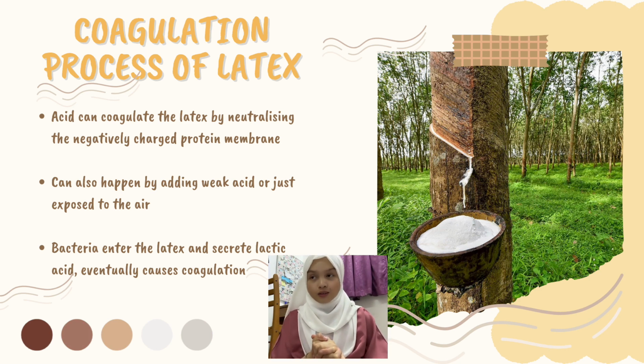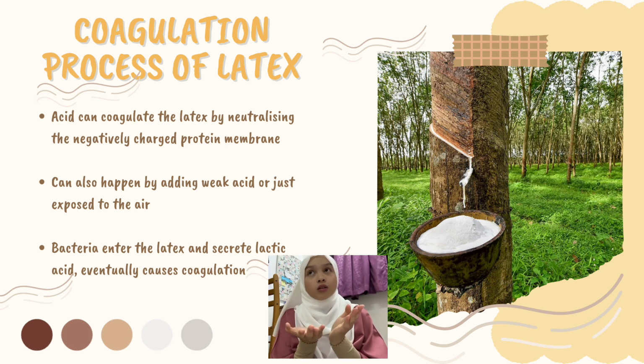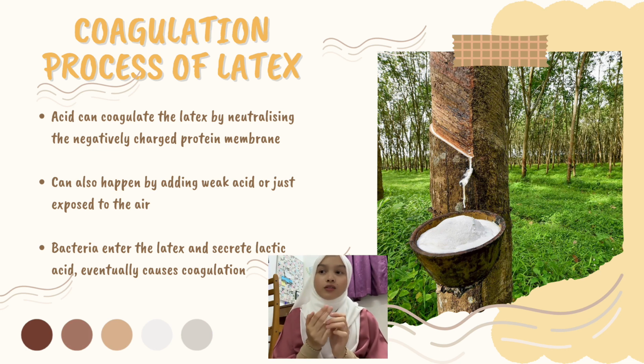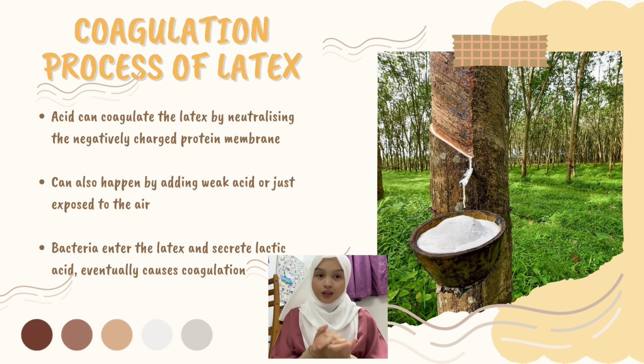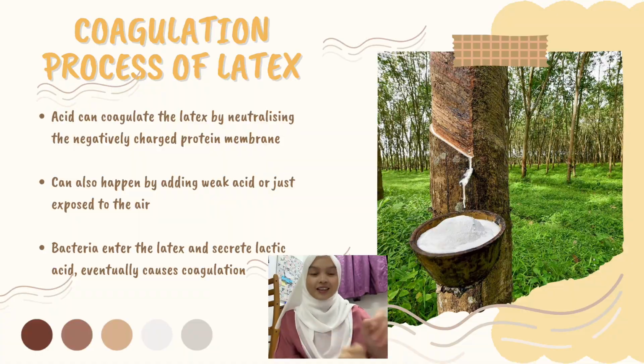This is because the acid in the latex can coagulate the latex by neutralizing the negatively charged protein membrane. It can also happen by adding weak acid or just being exposed to the air. Bacteria from the air enter the latex and secrete lactic acid, eventually causing coagulation.